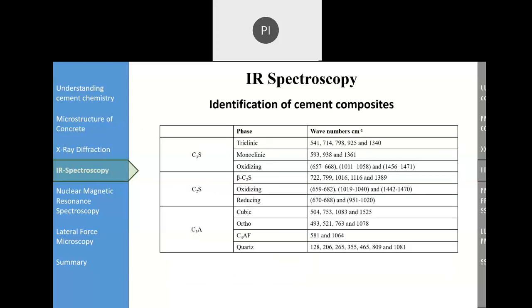At different wave numbers we will find different phases, even C3S can be observed at different wave numbers. So it's not just important that I have alite C3S in my cement and that's it. No. What is the phase in which it is present? Is it present in triclinic phase? Is it present in monoclinic phase? Or is it present in orthorhombic phase? Because that will again tell how much reaction has taken place, and how much strength we finally expect from C3S, because there might be one C3S with more triclinic and less monoclinic, and another with more monoclinic, less triclinic phase. So that will carry a lot of meaning. It's not just the total amount of C3S.